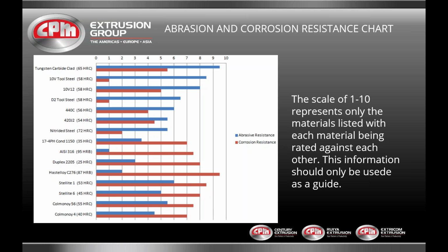As you can see, the tungsten carbide clad at 65 Rockwell is very abrasion resistant, moderately corrosion resistant. 10V tool steel is the same, with wear resistance much higher than corrosion resistance. This continues until you get down to the 17-4 and the 300 series stainlesses, the duplexes, and on down the chart, where you see the corrosion resistance creeping up and the wear resistance creeping down.